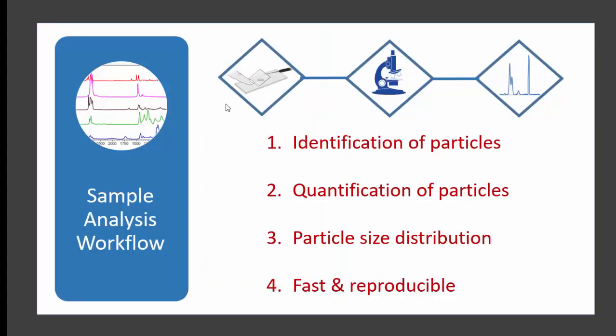And finally, we get to the sample analysis workflow. Regardless of what method we're using, whether it's micro Raman, micro FTIR, or GC pyrolysis, we want to be able to positively identify the particles, and the way we do that is against a reference library. You're not going to be able to quantify the number of particles using GC pyrolysis. You will get a total mass of the particle content, but if you're using micro FTIR or micro Raman, you will be able to count the individual particles. They will also allow a particle size distribution, which is going to be a beneficial feature. And provided you have a focal plane array or some instrument that's able to rapidly scan the slide, the results should be fast and reproducible.